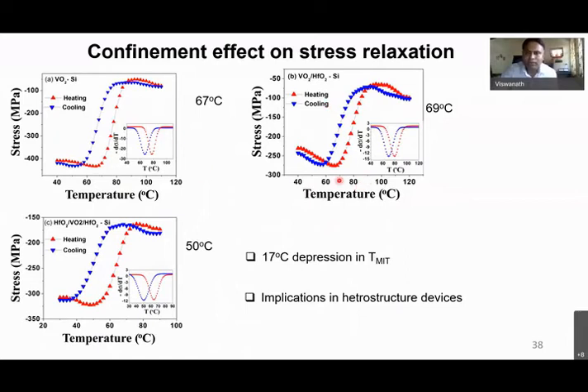Structural phase transformation also we have seen by looking at the wafer curvature. Again, there is a change in transition temperature of 17 degrees Celsius difference. So whenever we take any heterostructure, one has to be careful, or one can also efficiently use this method to tune the phase transformation temperature.